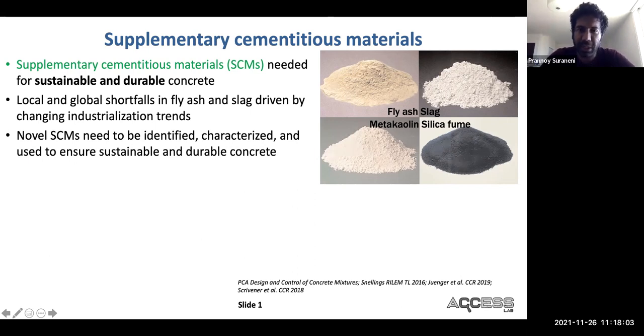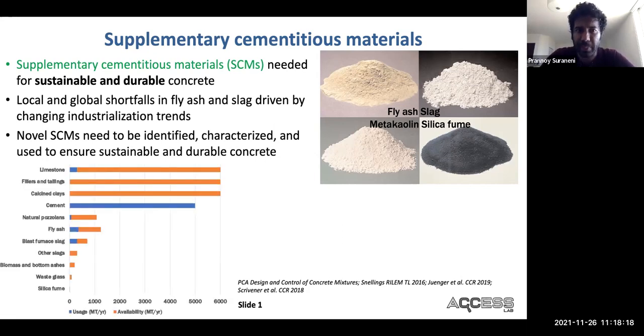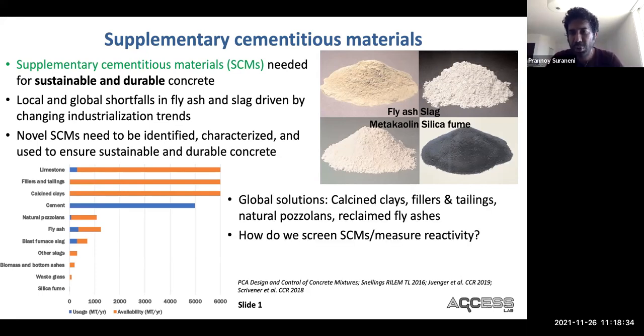The biggest push for sustainability, of course, comes because cement is responsible for about 8% of all global CO2 emissions. And by using supplementary cementitious materials, this number can be cut down greatly. So if you look at global availability of supplementary cementitious materials or materials which could be used as SCMs, you can see that fillers, tailings, limestone, calcined clays, natural pozzolans, fly ash are probably the most promising. And these are global solutions, but of course, local solutions are also important because there really are a lot of materials that are available in several millions of tons just locally, which are important for this consideration.